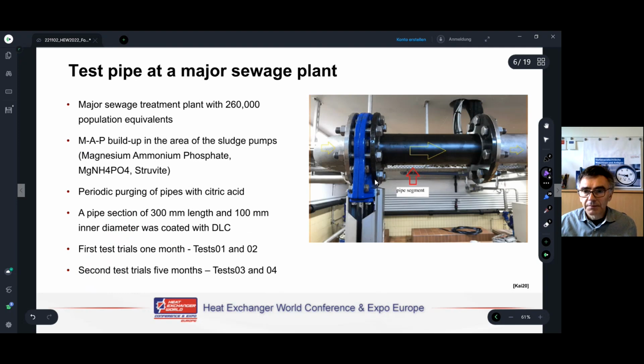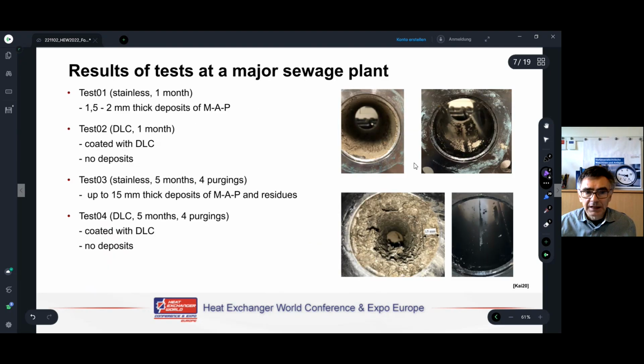First trials, I will go into this very shortly. We were at a sewage plant where they had really severe sewage problems. At the sludge pumping station, we had a test pipe 300 millimeters long, 100 millimeters in diameter. The results after 1 month: without coating, scaling. With DLC coating, no scaling. Just some sand here on the photo.